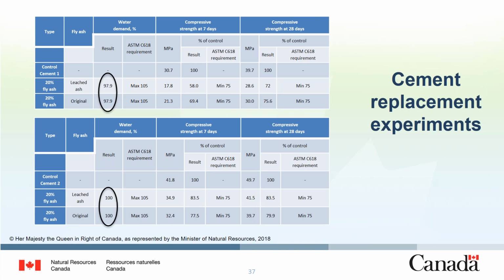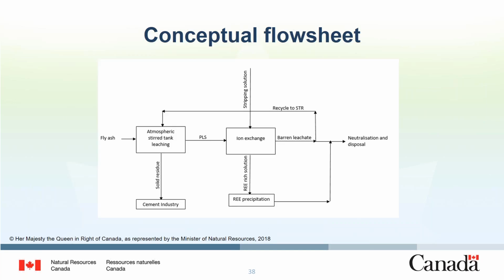With the first cement, both the 7 and 28 day compressive strengths are inadequate, as highlighted in the screen, which means that neither the original fly ash nor the leach material nor the leach residue are suitable to use as a replacement with cement 1. However, both are suitable to use as a replacement with cement 2. In fact, the leach material actually produced higher compressive strengths, albeit slightly, so it indicates that leaching the material produces a fly ash residue that actually performs better in the cement.